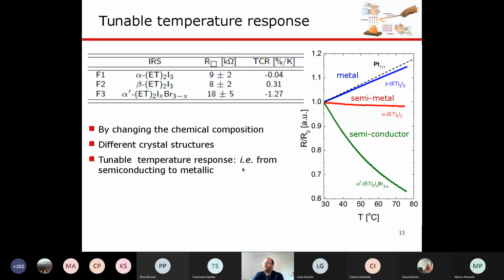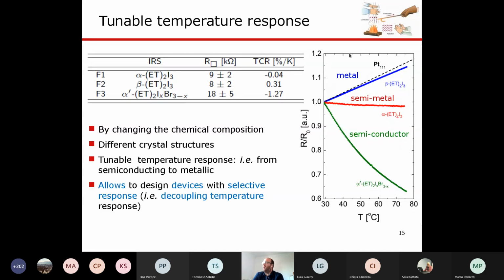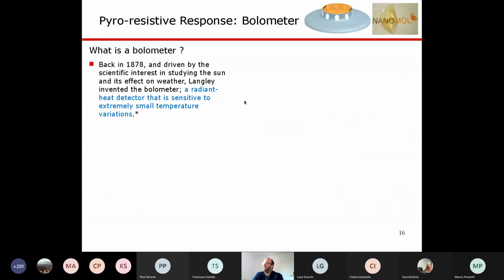Now, this is really interesting because all of them are also sensitive to deformation, but imagine you could use the red one and make a deformation sensor which shows the same response at all temperatures. So we can try to think about selective sensors. Now, more easily, we could also just put the green sensor on top of a surface. And this would allow us to directly measure the temperature of this surface. But we have been trying to make something even more fancy. So we developed, or we made, a bolometer.